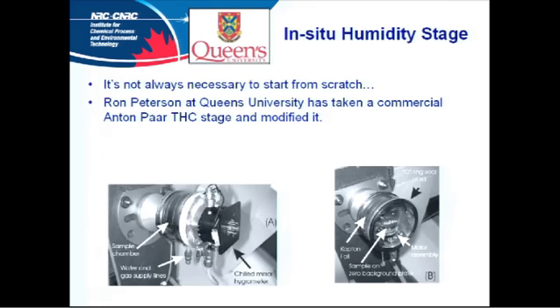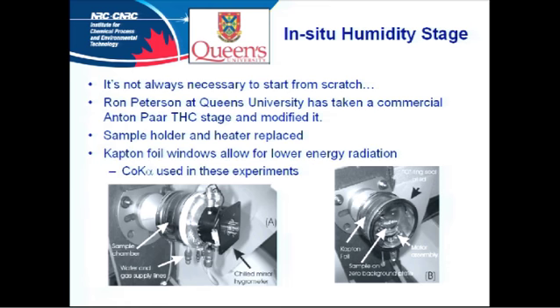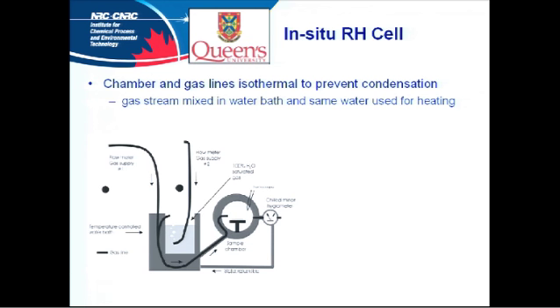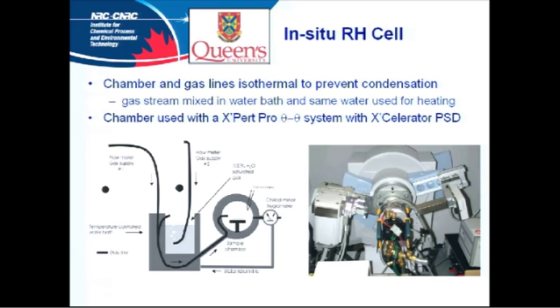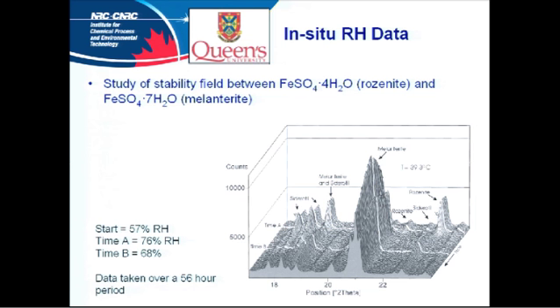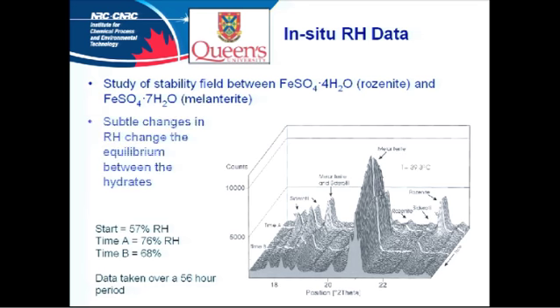In-situ humidity. You don't have to build it from scratch. You can just take something and modify it. They just replaced the sample holder and heater. Foil windows, rather than thick beryllium, mean that you can use lower energy radiations, so it's very material dependent, so they can use cobalt. And the trick here, in terms of relative humidity, is to keep everything isothermal, then you don't get any condensation. I think they're on the 9th iteration of this particular one, and this is set up on a Philips. And they get quite good data. These are very, very subtle changes in terms of what the relative humidity is, so this needs pretty close control. And this is basically iron sulfates, backwards and forwards.